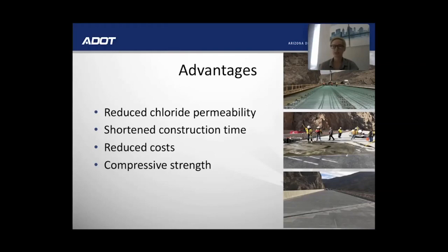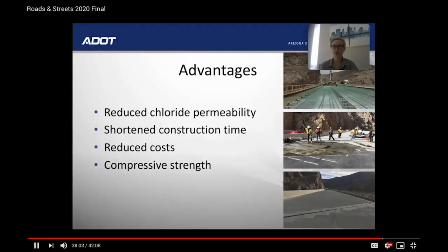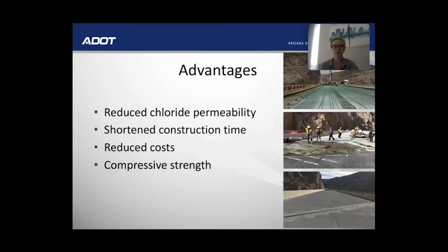By placing a monolithic deck, construction time is reduced by approximately 1 week. This reduction in construction time then allows for the placement of bridge decks later in the construction season. Reduced costs: the cost analysis performed showed that the placement of the full depth silica fume bridge deck was approximately 10% lower than the placement of conventional concrete. And actually, when research was being done in the Minneapolis and St. Paul metropolitan area, their cost analysis resulted in a 15% reduction in price for silica fume. So we are really seeing some impressive results throughout the country.